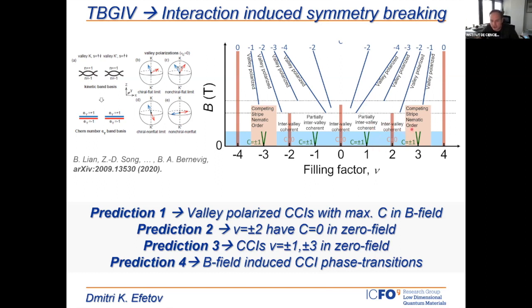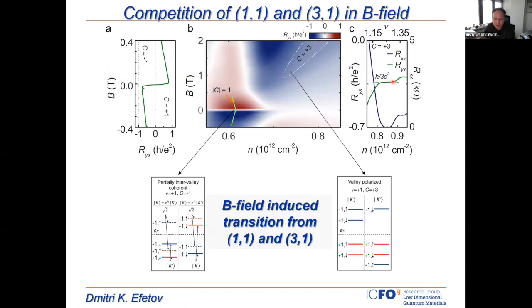So this is sort of the ground state. However, magnetic field strongly couples to the Chern numbers here, and it couples strongest to the larger Chern number. So each of these states goes over to a valley polarized state with the maximal possible Chern number, and therefore at these higher fields we observe these valley polarized states. And really, this is going back to our phase diagram here. This is what we observe in our measurements. At zero field, we get these low Chern number states with Chern number 1, which are given by this type of schematic where we assume a partially intervalley coherent state. Then if we increase the magnetic field, it couples strongest to the higher Chern numbers, and we obtain a valley polarized state where one valley is polarized with respect to the other, and therefore we also have a really strong contribution of orbital paramagnetism in this problem.